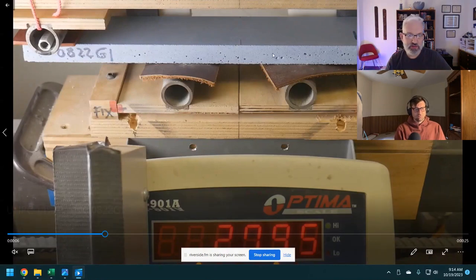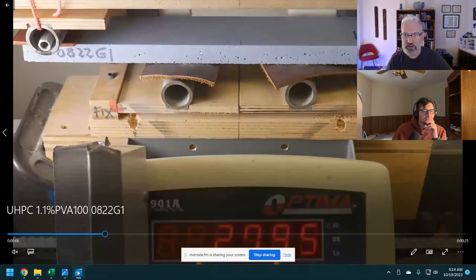And there you can see the relatively low volume of air voids in it. See the surface quality of it. Pretty darn good. There's no pinholes in it. Just to give you an idea, this is a 2-inch wide sample. It's 14 inches long. Test program center to center on the top is 12 inches. Center to center on the bottom is exactly 4 inches. So everything's very, very precise, even though it doesn't look like it is.